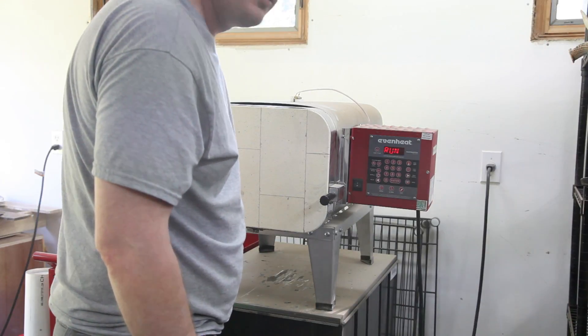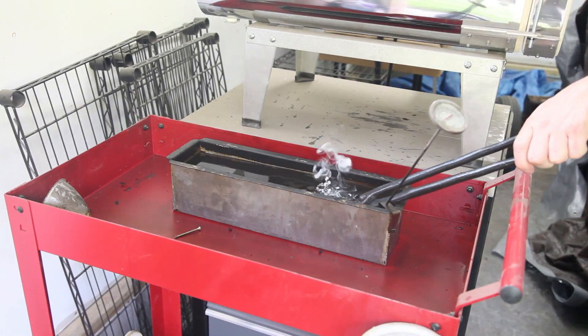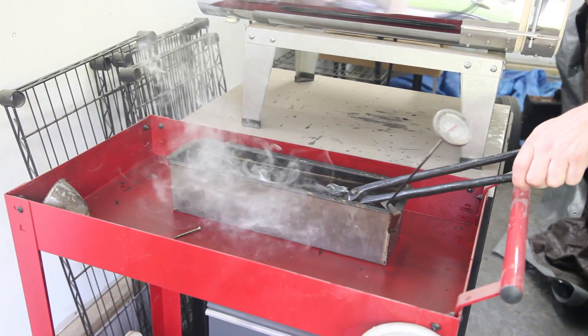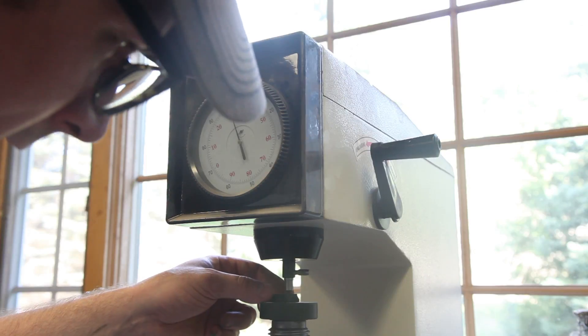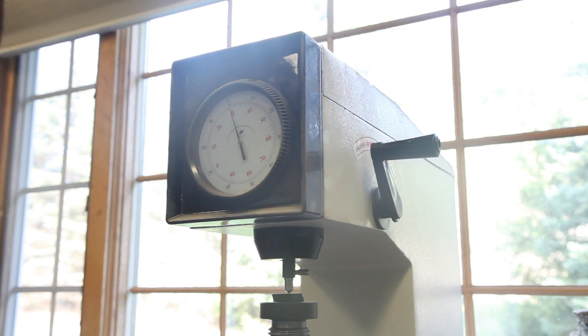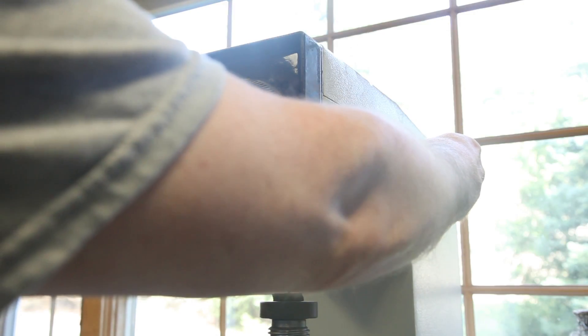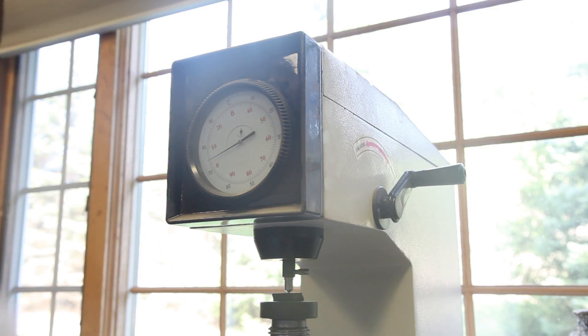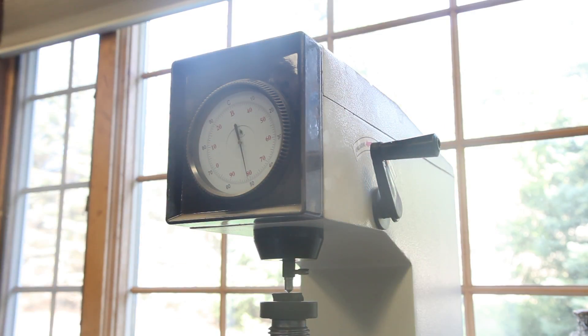Let's give it a shot. Boom, into the oil it goes. As before, I ground away the surface stuff. Let's see if we hardened it at all. So we started at 18, and where are we at now? Oh yeah, 51. So yes, you can harden this stuff, so yes I can make a knife out of it.